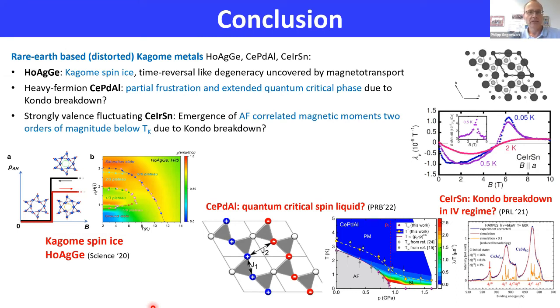structure type. And in cerium palladium aluminium, I showed you evidence for a finite regime in the temperature-pressure phase diagram, where we have spin liquid correlations proven by muon spin relaxation, and where we also see quantum critical behavior. So that's a type of quantum critical spin liquid.